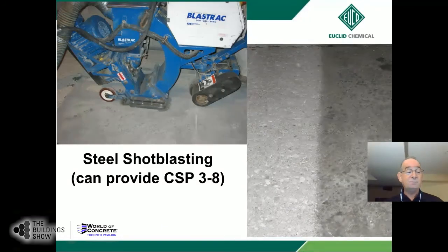This is a typical shot blast machine that is used to abrade the surface. Steel shot is used almost like sandblasting, except it's a self-contained system with a vacuum hose that extracts all the dust and debris. And on the right side, you can see the dark area hasn't been treated. The piece on the left side has been shot blasted, so it's now got an appropriate texture for this.